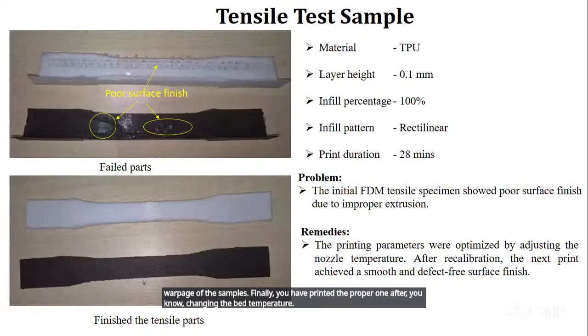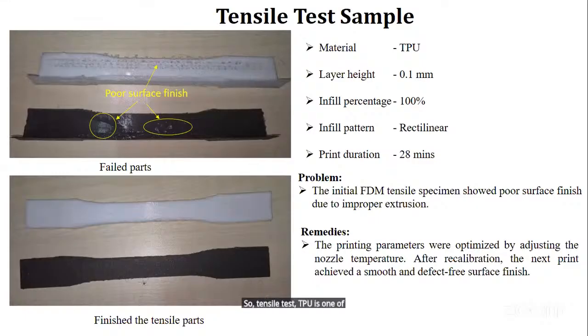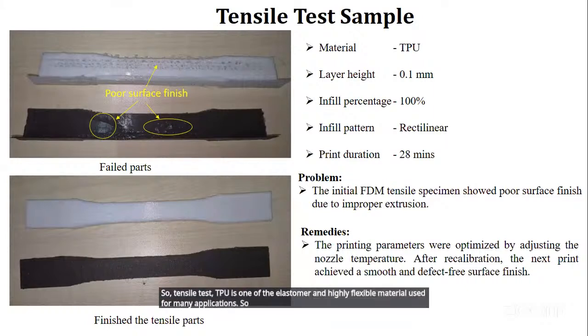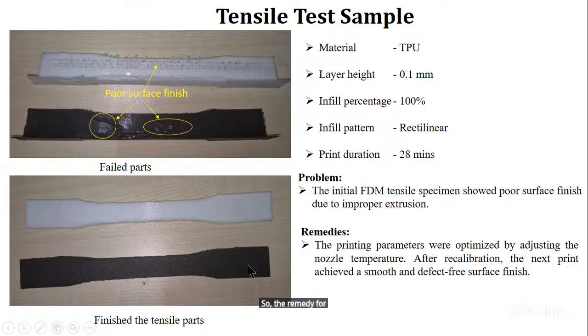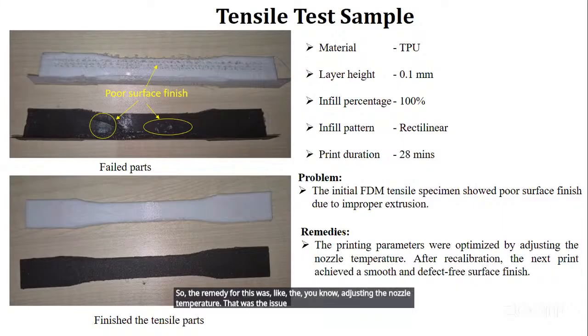For the tensile test, TPU is one of the elastomers, a highly flexible material used for many applications. We tried to print this virgin TPU material with this process parameter. This sample was taking 28 minutes, but you can see there are some issues like poor surface finish and stringing and all those things which are happening. The remedy for this was adjusting the nozzle temperature. That was the issue, and recalibration of the printer was also necessary, so that we obtained the final finished tensile samples with good surface finish of this TPU material.